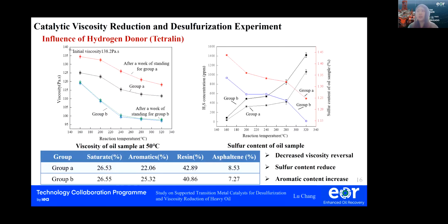It shows that the addition of a hydrogen donor inhibits the rebound of the viscosity of the oil sample after the reaction. That's because the combination of hydrogen atoms in the hydrogen donor with the reactive free radicals inhibits the polymerization reaction of the hydrocarbons. And the second graph shows the influence of the hydrogen donor on heavy oil desulfurization. And the sulfur content in the oil sample after the reaction of group B decreases significantly.